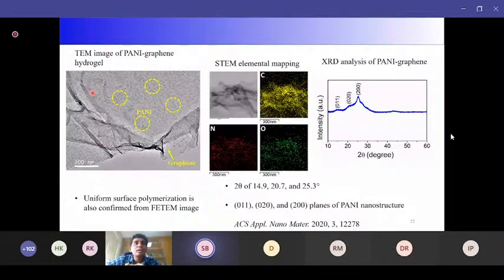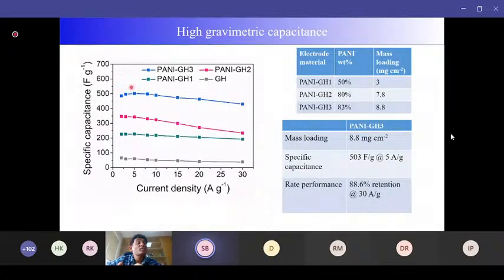And as you can see right now, we targeted the specific gravimetric capacitance. As we mentioned, because we have downsized it, and also because they are directly coupled with the graphene, we can increase the specific capacitance. We have achieved specific capacitance up to 503 farad per gram. Previously it was around 350 farad per gram, but because of this particular strategy, we can increase the gravimetric capacitance to a large extent.